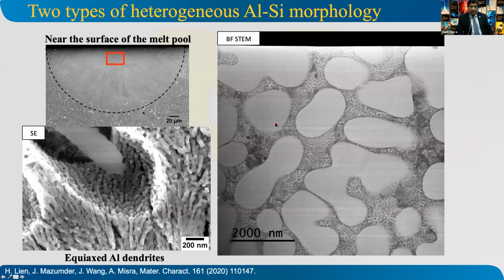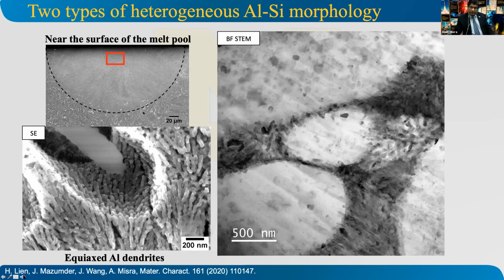In the other one, where you get this two-phase structure where you have eutectic with the primary aluminum, notice that this looks like a hypo-eutectic, which is you form primary aluminum, even though the composition is hyper-eutectic. And that's just an effect of far from equilibrium solidification. Very rapid quenching can do that. It can change what you would expect from an equilibrium phase diagram. But what's interesting is that sometimes inside those aluminum dendrites, you start to see these fine precipitates. Those turn out to be silicon precipitates. So we have only two elements, aluminum and silicon, so that's what will form. So you get silicon forming as these fine precipitates.